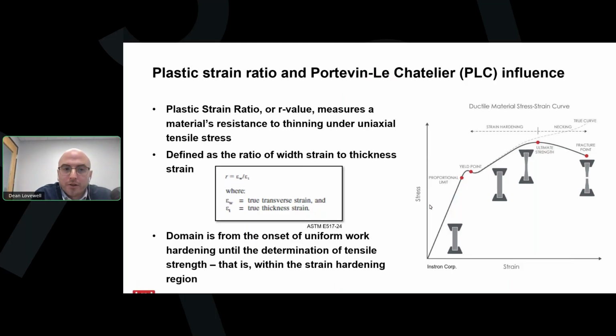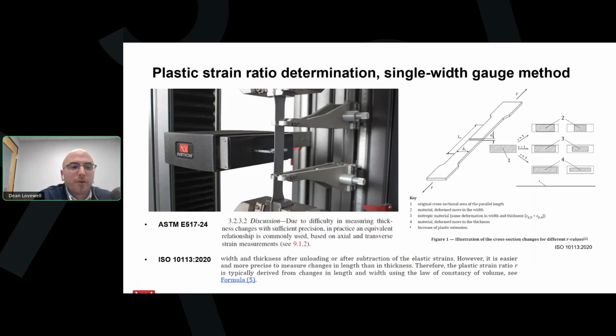Now, although the calculation here defines the ratio as transverse strain divided by thickness strain, testing standards clearly specify that R value is not typically characterized from the direct measurement of the thickness. This is because it would be extremely difficult to measure the change in thickness for thin sheet metals.